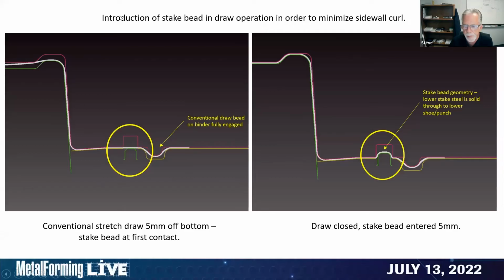Sure. Yeah. So this is an example of the introduction of a stake bead in a draw operation. This has helped us considerably reduce curl and spring back in some of these higher strength parts. In the screenshot you see on the left, this is the draw off bottom. You can see the conventional bead geometry in the, let's say, the downward direction. And then just to the left of that is the introduction of a stake bead. So this is 5 millimeters off bottom. The green geometry on the bottom there is the stake bead itself.